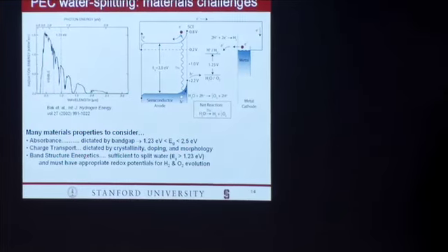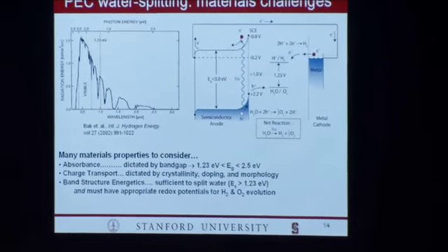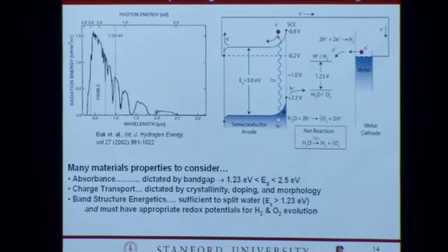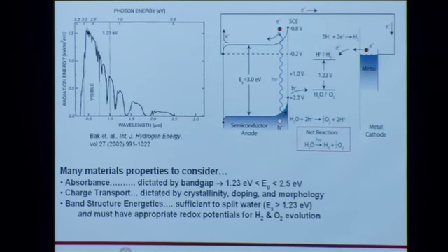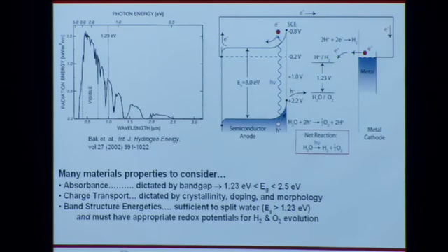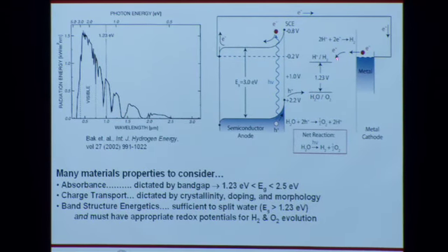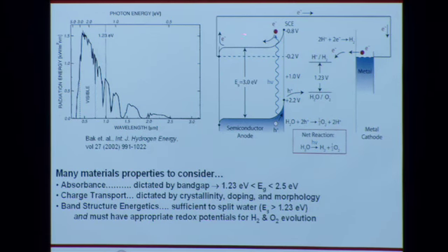We also have to think about the band structure energetics, meaning it's not just the band gap of the material that we think about. In the solar photovoltaic world, that's all that people need to think about: what is my band gap of the semiconductor? Here, we're actually trying to drive redox reactions of very specific potentials versus some absolute scale or some reference scale. And our conduction band better be high enough such that when we excite an electron, that electron will go downhill to reduce protons to H2. And our hole left behind is low enough in energy such that we can pluck electrons from water to make O2. So it's not just what the band gap is. We have to know physically where these bands are located versus the redox potentials of interest.